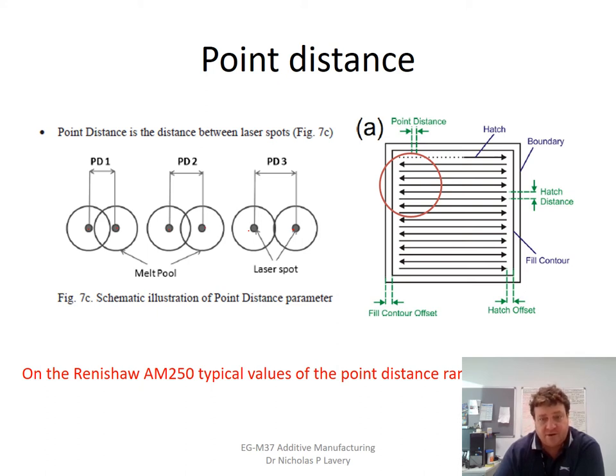On this particular diagram, you can see the point distance, and you've got a meander hatch pattern where the laser comes down, and then goes back, comes down, goes back, etc. So the line speed is determined by how far the spacing is between the points and how long it takes to run.